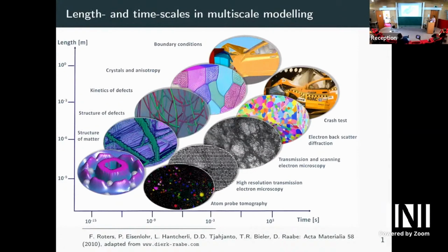We do geometric models of polycrystals. So essentially, you have these electron backscatter diffraction measurements, which tell you, if you have, for instance, steel, what the grains are, what the orientations are, and we use optimal transportation theory to very quickly generate artificial microstructure that resembles the real one as much as possible, so that if you can generate an ensemble of artificial microstructures, then you can quickly do homogenization and pass it on to a higher scale.